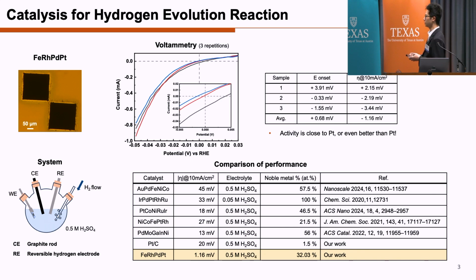And we can see that our overpotential value is the lowest. And we also lowered the noble metal percentage in our work, which shows that our work is pretty promising. For future direction, we can provide some theoretical calculations from density functional theory and maybe calculate the adsorption energy of protons, and we can further verify this result. Yeah, and that's all.